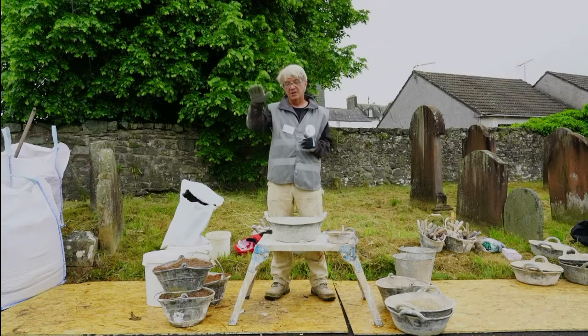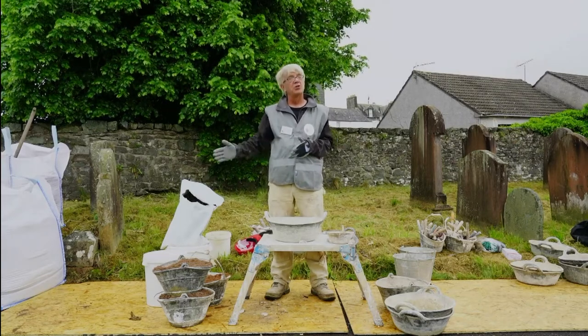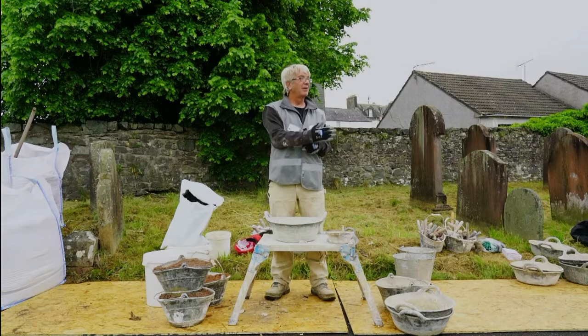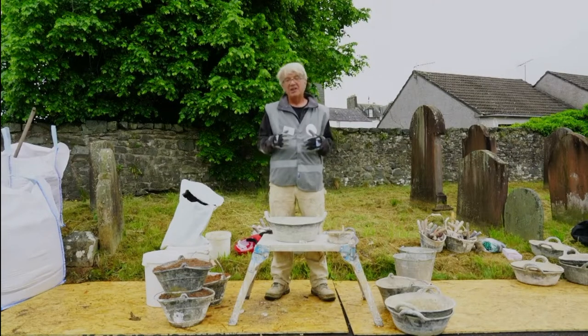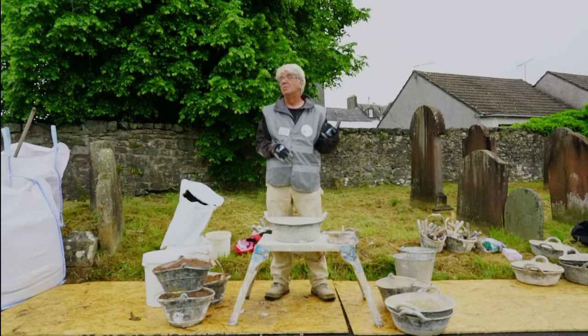They looked at a number of NHLs. They tested the desorptivity, which is unusual. Most people just test how easily it'll absorb water, which doesn't tell us very much, actually, in terms of capillarity. You need to know how quickly that water leaves once it's been wet. They did that, and they used a 1 cement, 3 lime, 12 sand mortar as a control.